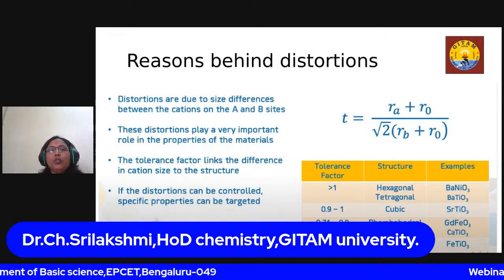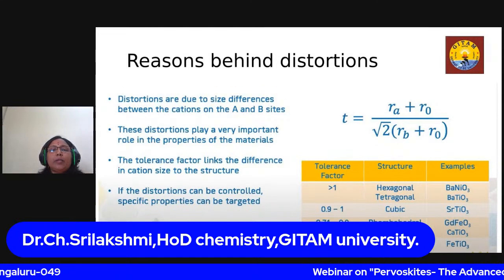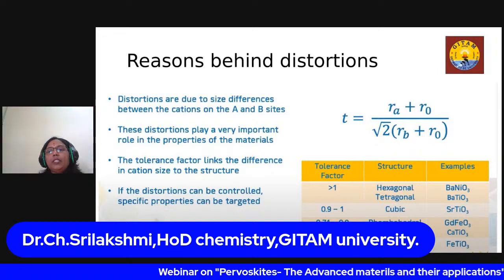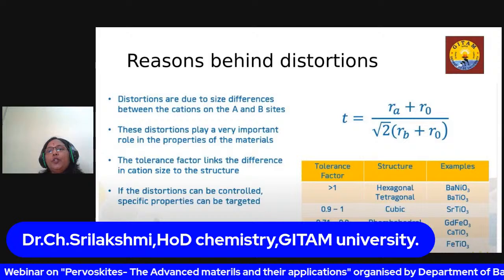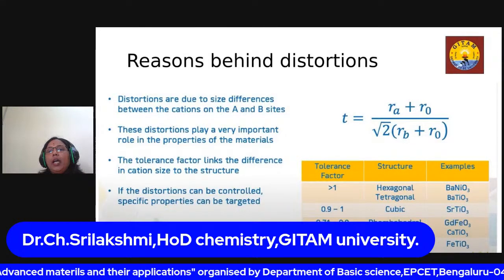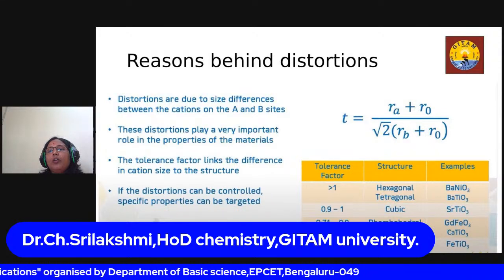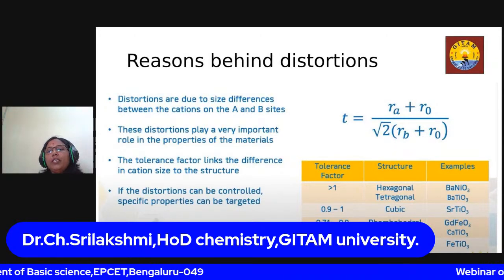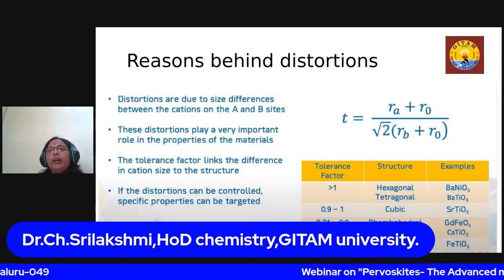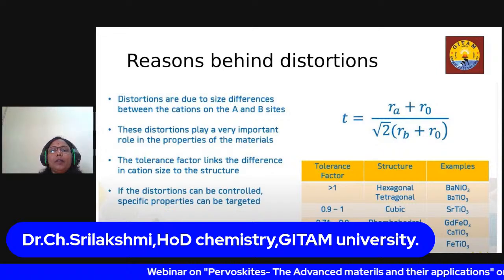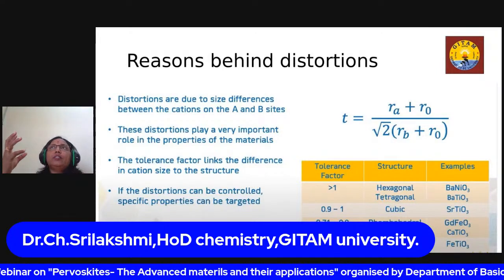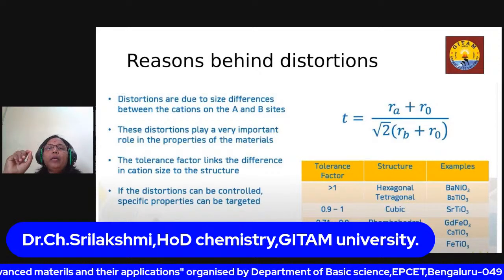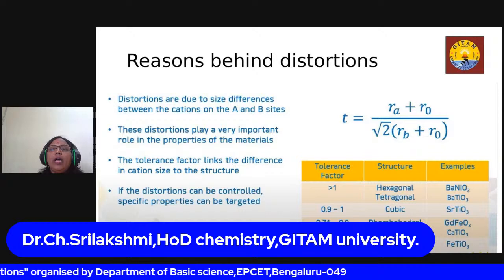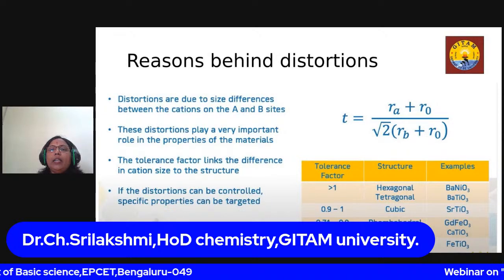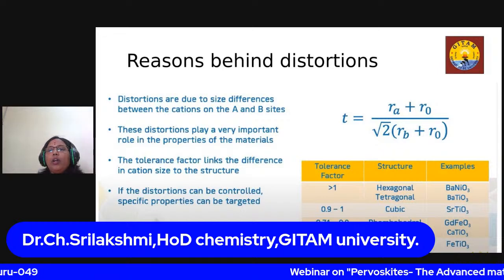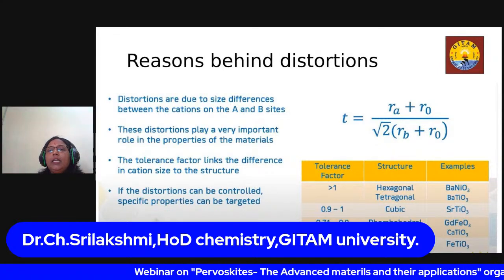These distortions can be controlled, and if you can control them, specific properties of these materials can be achieved. The tolerance factor should be between 0.9 and 1 if you want to prepare a cubic structure. If it is greater than 1, it forms hexagonal or tetragonal crystal structures, and so on. If it is 0.74 to 0.9, orthorhombic and rhombohedral structures will be formed. So you can always target a structure. Suppose a tetragonal structure is really suitable for your application; based on this, you can choose the elements, fit them in here, and calculate accordingly.